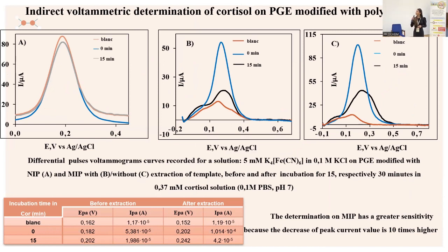Fourthly, in the case of using non-imprinted polymer electrodes, the decrease of the signal didn't vary significantly, so these kinds of electrodes can be used for this determination. On the other hand, in the case of using molecular imprinted polymer electrodes, the indirect determination was realized without and with extraction of the template in ethanol. So, as you can observe, the peak values were higher for the molecular imprinted polymer electrodes after extraction, and the difference between the first and second peak was 10 times higher, which suggests that this kind of electrodes have shown greater sensitivity.